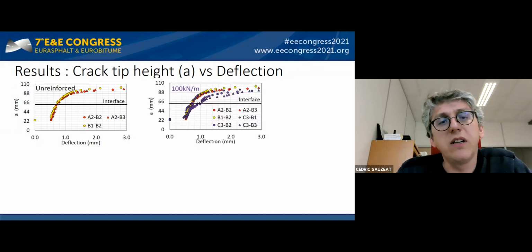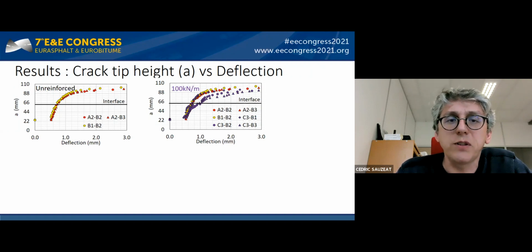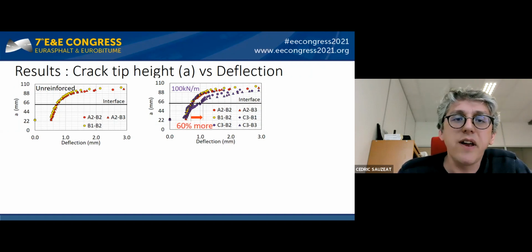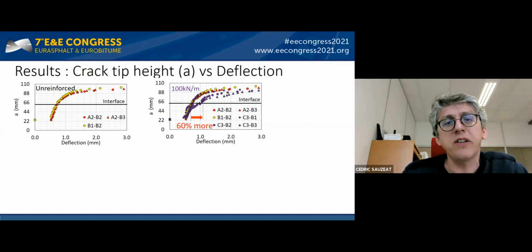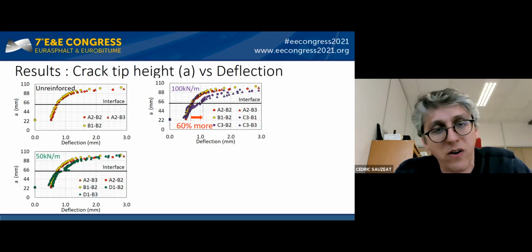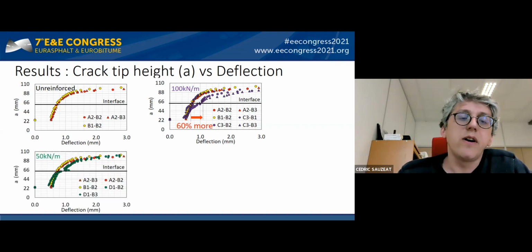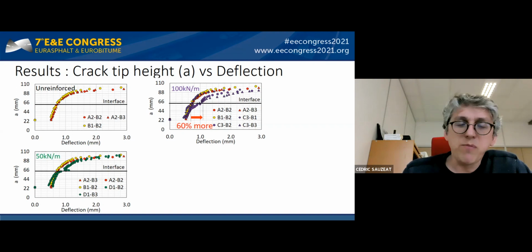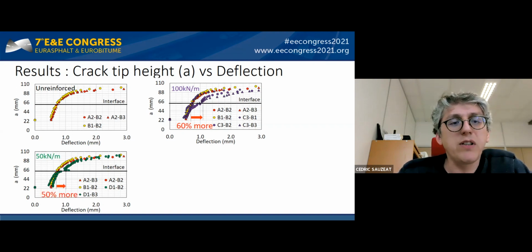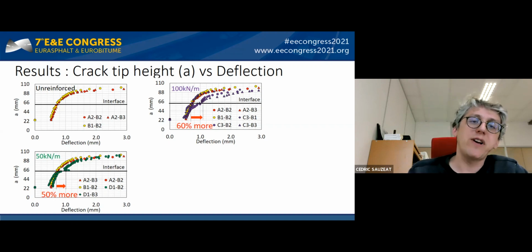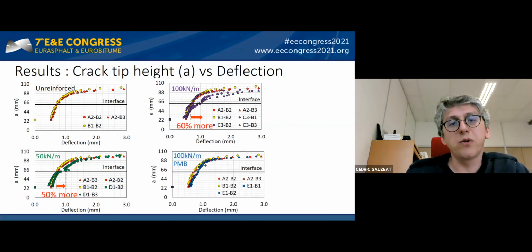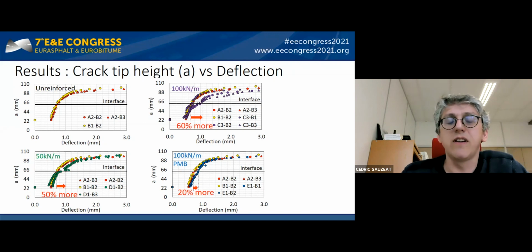But when you analyze the result for the reinforced specimen, you can see that there is a small delay in the crack propagation. You can gain 60% more deflection here for the 100 kilonewton per meter strength geogrid specimen. You have the same results, but only 50% more delay in deflection for the 50 kilonewton per meter strength. And here the result for the 100 kilonewton per meter strength geogrid with polymer modified bitumen.